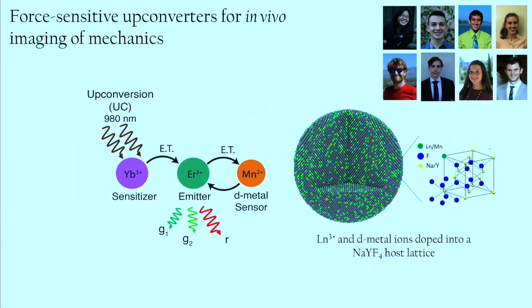And then, of course, ruby, some of you may have worked with ruby before, is alumina with chromium impurities. So our idea was to combine the upconversion properties of the lanthanides with the sensitivity to the surrounding crystal field or the surrounding environment of D metals. So we take ytterbium and erbium, which absorb in the near infrared, in this case at 980 nanometers, and then erbium emits in the visible frequency regime, usually in the red and green, and then we have a D metal sensor that's very sensitive to the surrounding pressure.